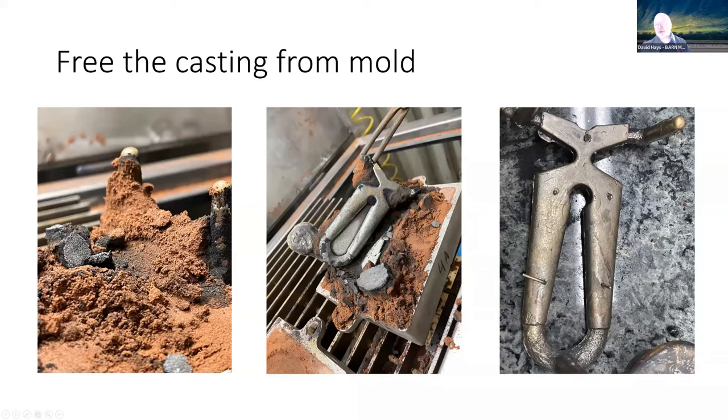There's a tube connecting the sprue blob down into the U-shape — that tube is actually molten bronze, and then it goes in and fills the pattern. That way you aren't pouring directly into or disturbing the mold — it's just flowing in. You don't want the dynamic pressure from the molten metal deforming the mold, so you pour it in on the side and let the molten metal run in.